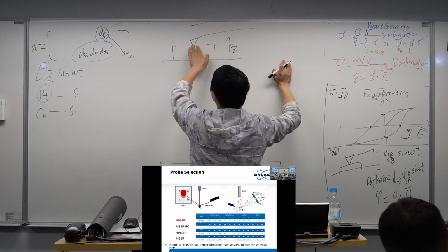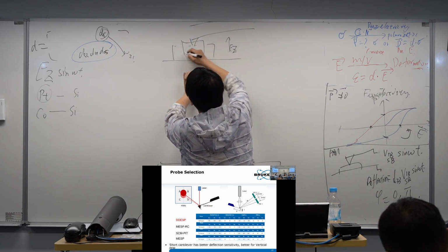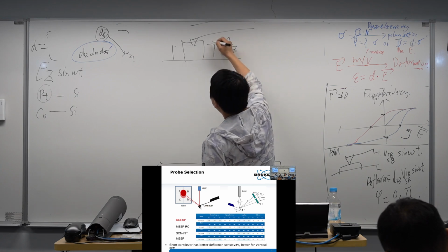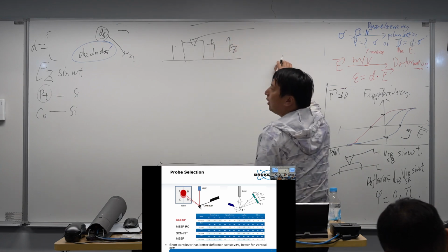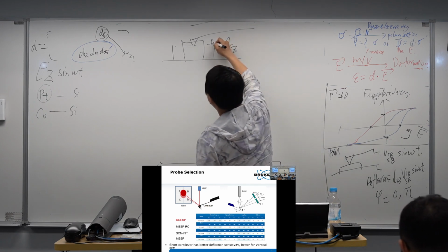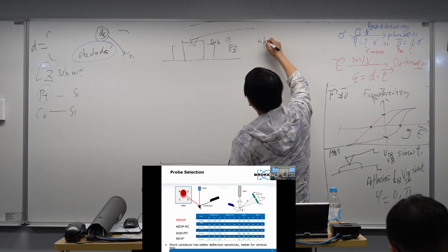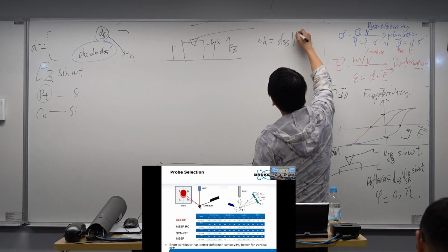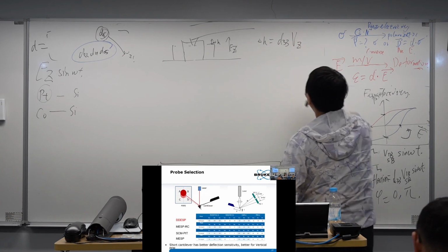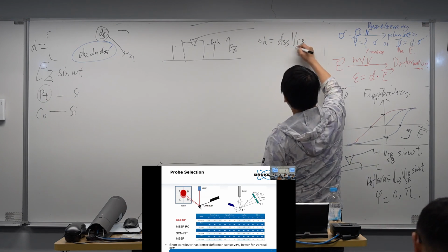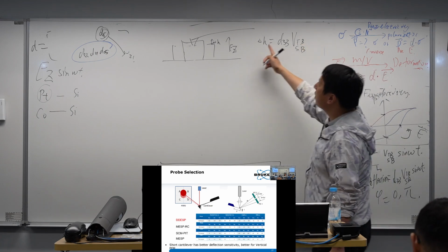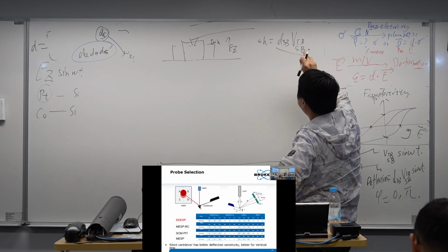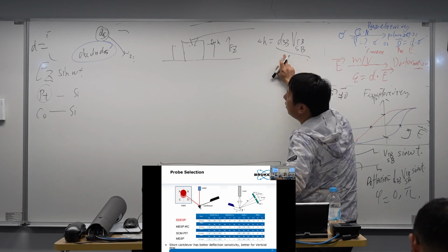The expansion changes the height, and I will call this change in height delta H. The delta H is defined by D33 and the voltage, VTB or VSB. So this delta H is a fixed value, determined just by your parameters and the D33 itself.